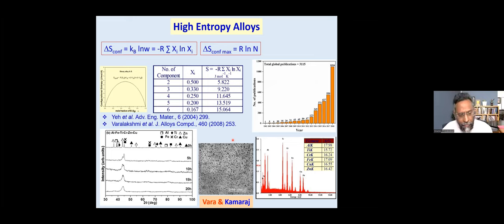So here, if you take these six elements and start ball milling, after some hours of ball milling, the X-ray diffraction pattern at the bottom left says that you start with a number of elements with so many peaks, and suddenly you end up with just one set of peaks which correspond to BCC.